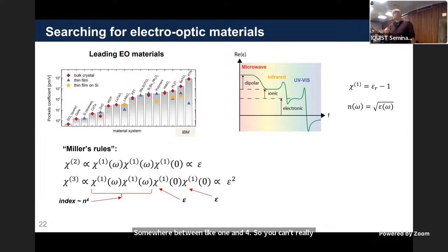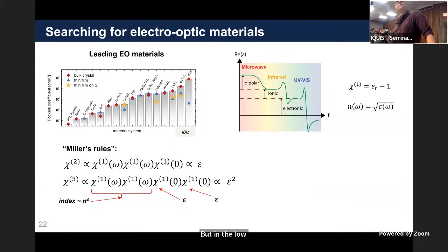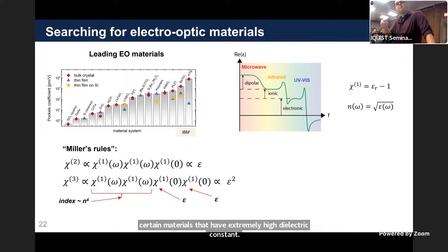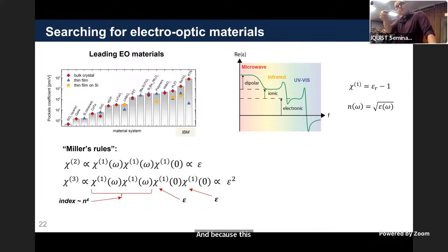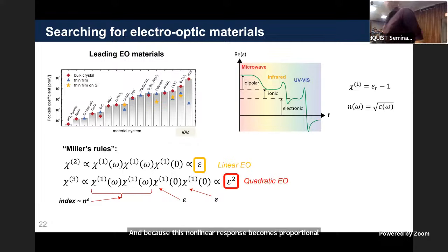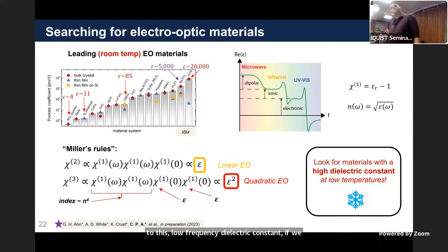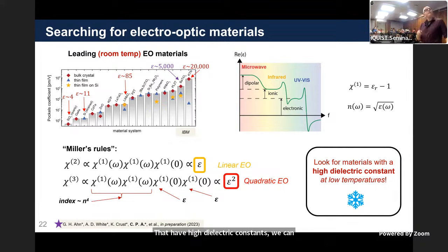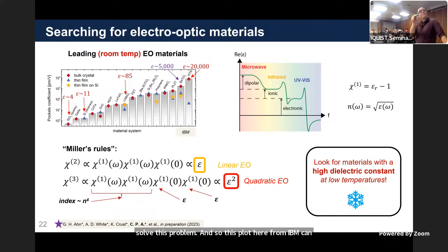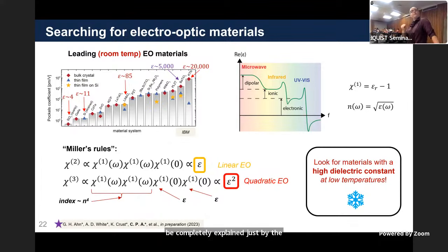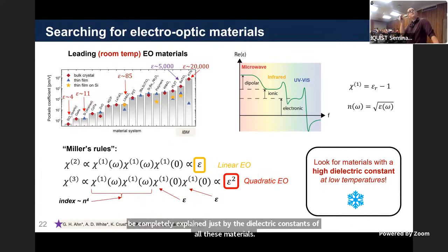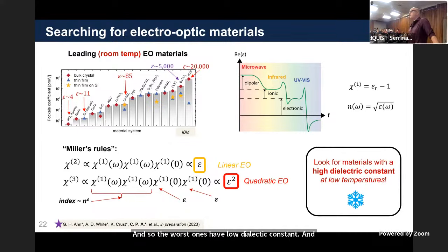But in the low frequency microwave regime, there are certain materials that have extremely high dielectric constant. And because this nonlinear response becomes proportional to this low frequency dielectric constant, if we simply find materials that have high dielectric constants, we can completely solve this problem. And so this plot here from IBM can be completely explained just by the dielectric constants of all these materials. The worst ones have low dielectric constant, and the high ones have high dielectric constant.